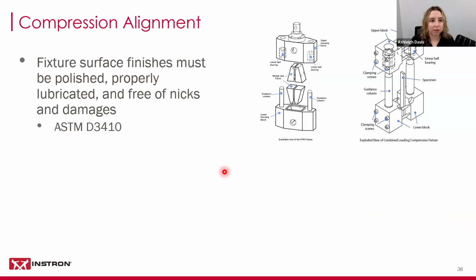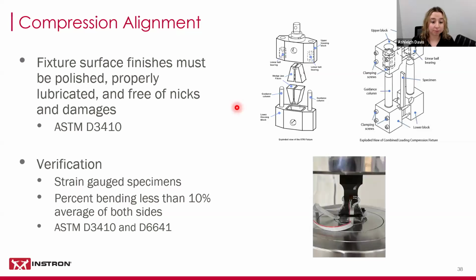As Stephan was talking about before, in terms of our fixtures and our specimens, we do want to make sure that our fixture surface finishes are polished, properly lubricated, and free of any nicks or damages. And then lastly, if we are going to be doing compression testing with bonded strain gauges, there is guidance in ASTM D3410 and D6641 that indicates that your percent bending, so if you have a bonded strain gauge on either side, the average of the bending moment needs to be less than 10%. And when you're less than 10% upon initial loading, it's okay to use the bonded strain gauges to report out the strain values that you're seeing within the compression test. And again, this is indicated in D3410 and D6641 if you want to check out more about that.